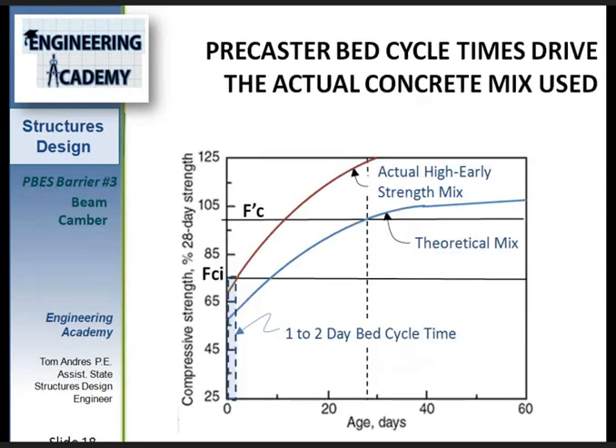And certainly another factor influencing camber is the concrete mix design. It is the release strength, not the 28-day strength, which typically controls the mix design that precasters choose to use because they want to turn around their beds, right? Therefore, the designer assumes one strength gain curve to determine camber and buildups, but the actual strength gain curve is actually higher or stronger.